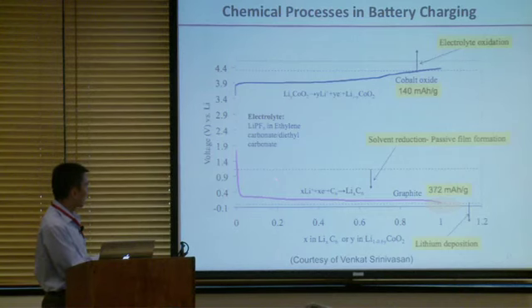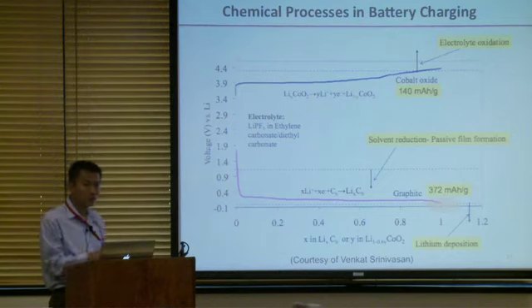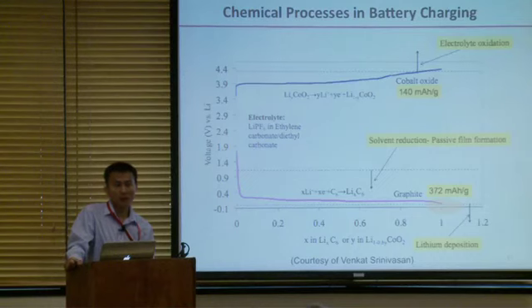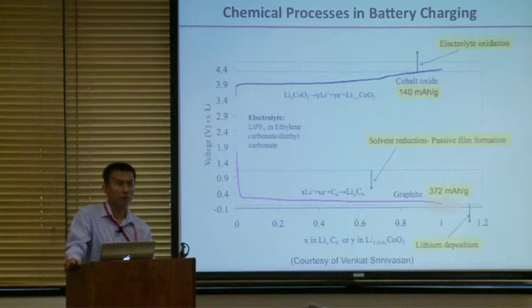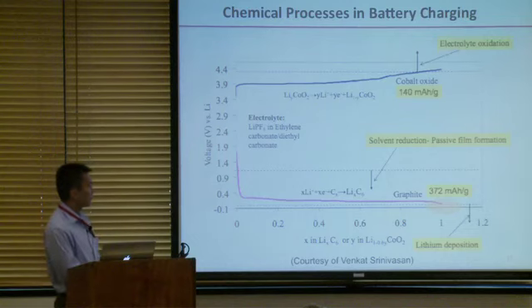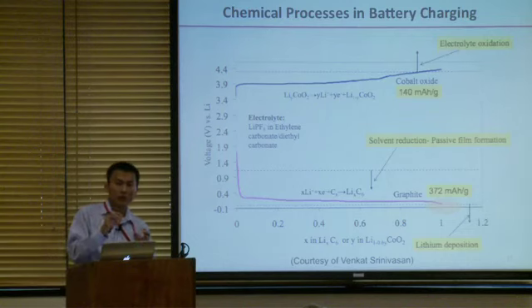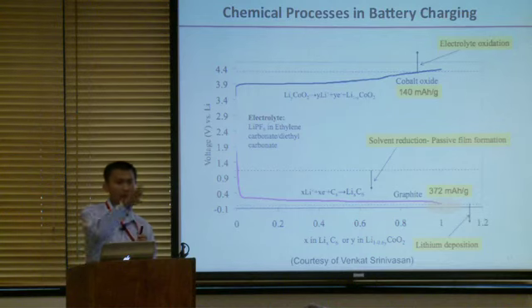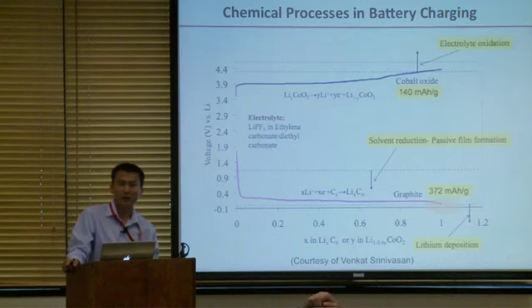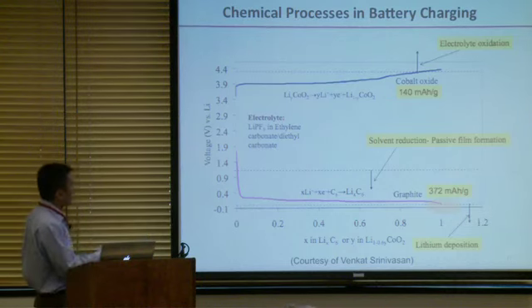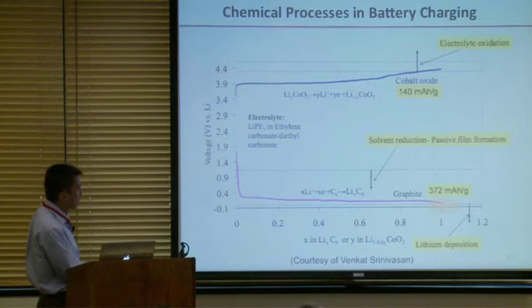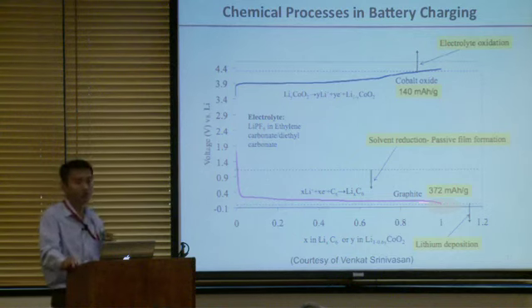Now when you get down in this voltage, you get more and more lithium going to carbon, right? If you put more and more lithium in, let's say you hit this dashed line right here. That's the 0 volt versus lithium metal, and at that voltage, you start to have lithium metal deposition, electroplating onto carbon, start to form lithium dendrite. And once you deposit a metallic structure, the metallic structure grows in a filament manner. It shorts your battery, it catches fire, it causes explosion. So you need to control your charging voltage, not go over to the degree you have lithium metal deposition.